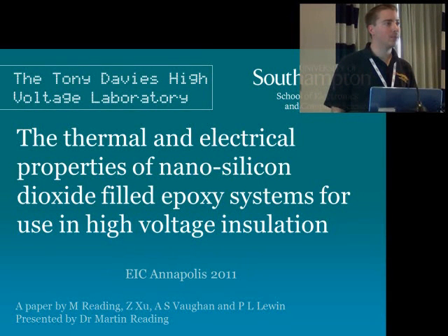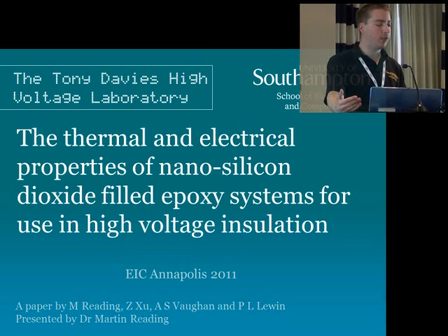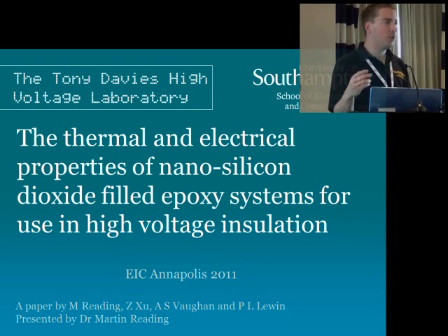For example, if you were to preheat your samples for a few days, we've been doing that for the same reason, to drive any moisture. Yeah. Well, that's definitely one thing that we want to look at. We were thinking that we would probably, if we bake or just warm the filler, just try and remove any of the water before we then put it into an epoxy. The epoxies do go through a drying process before we test them, just to make sure, because obviously one of the main problems with epoxy is water uptake. But you try and remove the water once the filler is in the epoxy.